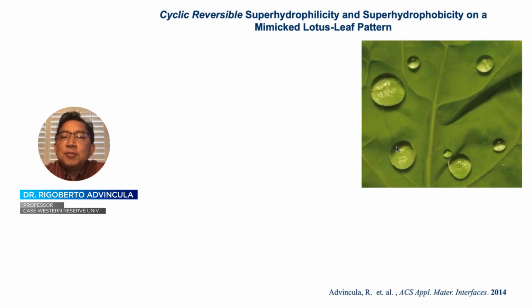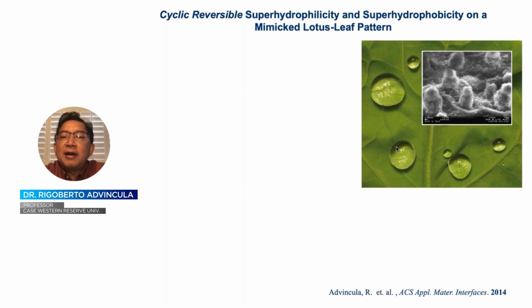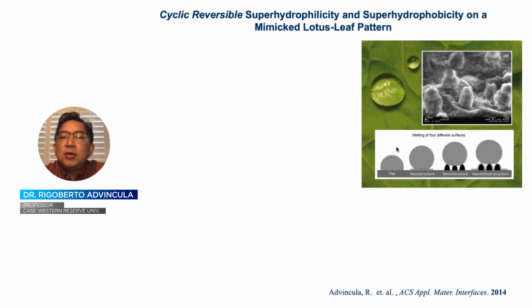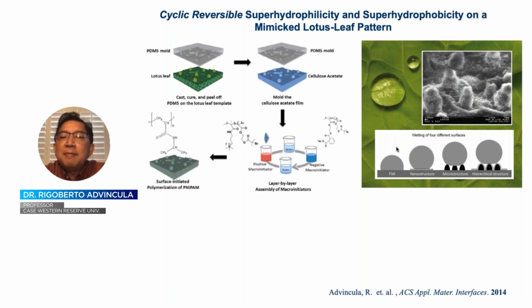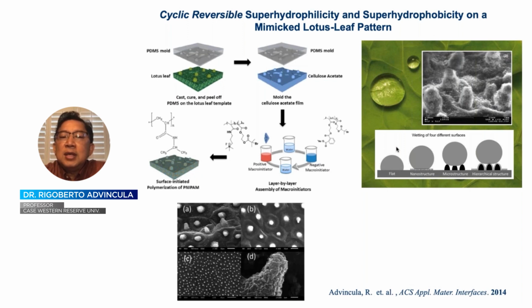The lotus leaf is known to be a super hydrophobic surface simply because of the hierarchy of roughness and the failure to form a continuous line tension or entrapment of air. And this is well known as the Cassie-Baxter phenomenon or condition. So for example, to produce a stimuli-responsive lotus leaf, we mimicked the surface of a lotus leaf using the chemistry I previously described, which is the grafting of polymer brushes and polyelectrolytes, the result of which, as shown in the SEM image below, is an artificial lotus leaf that has stimuli responsive properties.